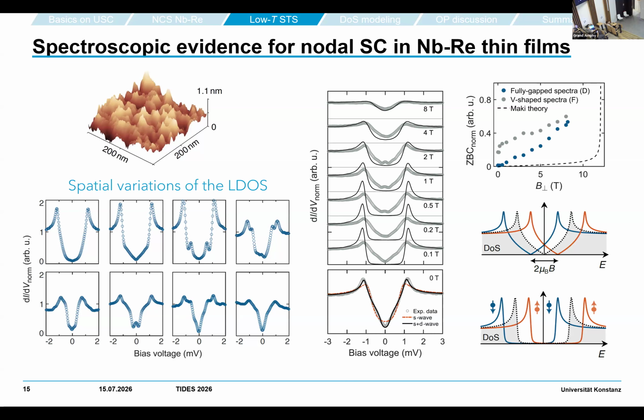Here's one example of one of these more or less V-shaped spectra. The experimental data are the data points, this is at 0 Tesla. The orange curve is the best fit assuming a single S-wave order parameter - you see it doesn't work. It is already much better when we assume a superposition of an S-wave and a D-wave. Then when we apply magnetic field, we do see that the gap is filled, and we can do this also for different spectra.